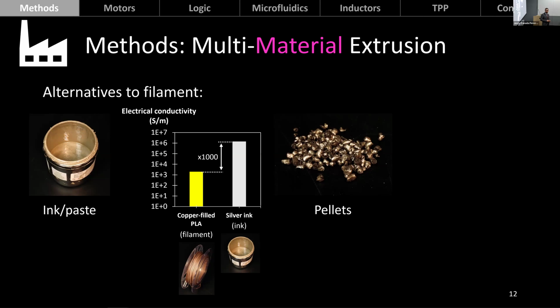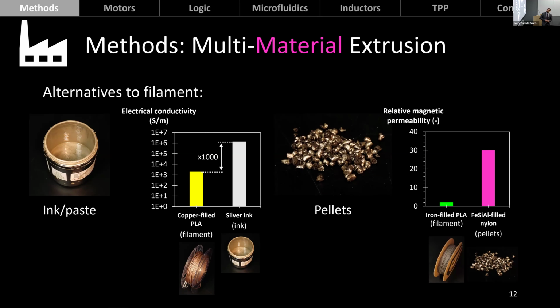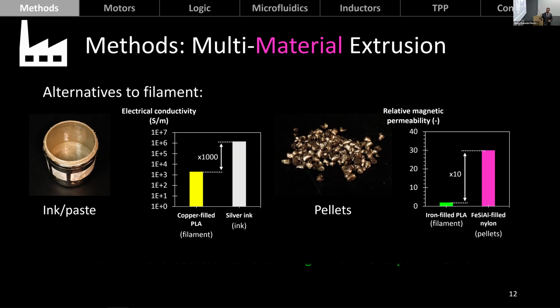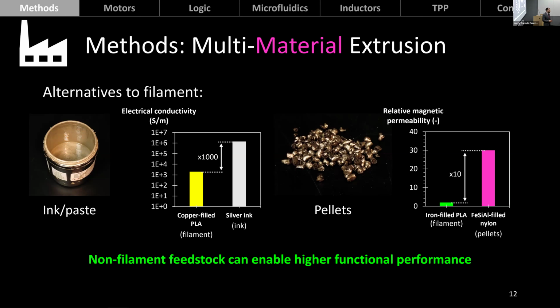And as you can see, there is a 1,000 times difference between their performance. So a pretty big gap. And if we look at this material, which is magnetic, and we compare its relative magnetic permeability, we see that between the filament and these pellets, there is a 10 times gap in performance. Now, let me mention that this material is soft magnetic, so it's not the one that you would want to use for making a permanent magnet, but instead the one that you would want to use to make magnetic cores. So not generating magnetic fields, but instead strengthening them and channeling them. And an important figure of merit to look at in those materials is the magnetic permeability. So if we are able to print with these non-conventional materials, at least when we're talking about 3D printing, then we would be able to access much higher performing materials.